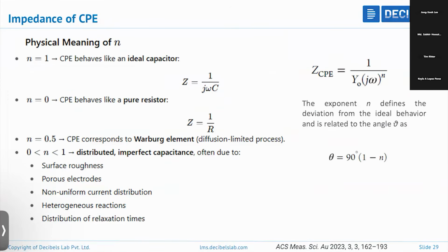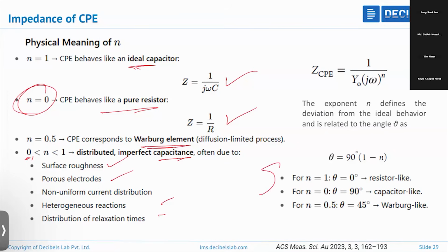The physical meaning of CPE is that if n is equal to 1, the CPE behaves like an ideal capacitor. If n is equal to 0, then CPE behaves like a pure resistor. If n is equal to 0.5, it behaves like a Warburg element. If n is between 0 and 1, it is distributed imperfect capacitance. It's often due to, as I mentioned, surface roughness, porous electrode, and various other practical issues. So this is a takeaway from this discussion.